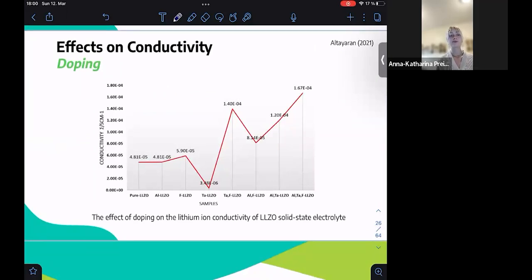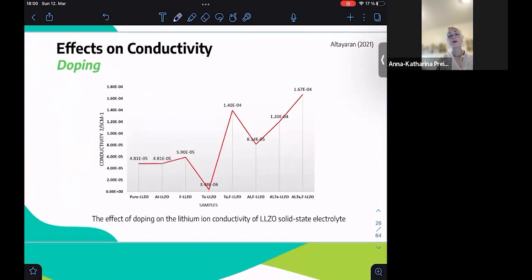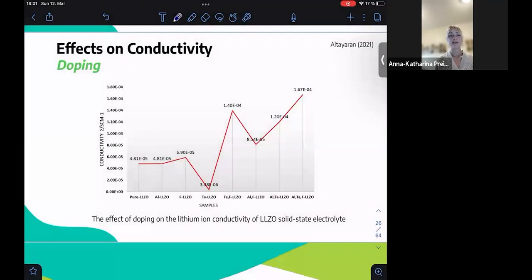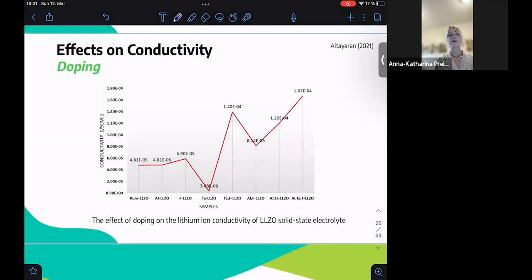Here, the researchers performed various dopings on that garnet electrolyte that I showed earlier, and they found that the best total ionic conductivity was achieved with multi-doping that garnet electrolyte with aluminum, tantalum, and fluorine. And basically, they concluded that doing this stabilized diffusion intermediates and provided vacancies in order to promote ion flow.